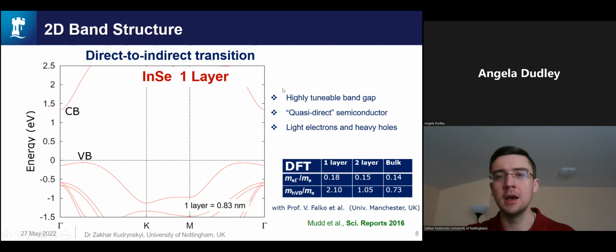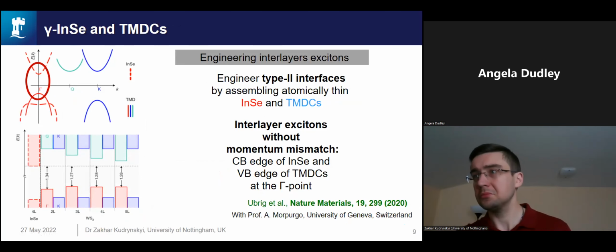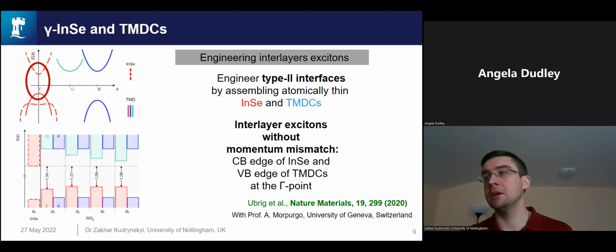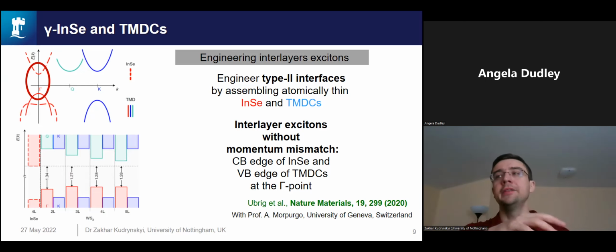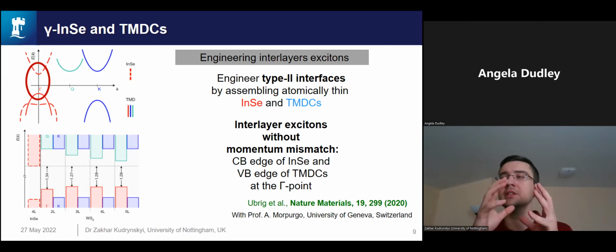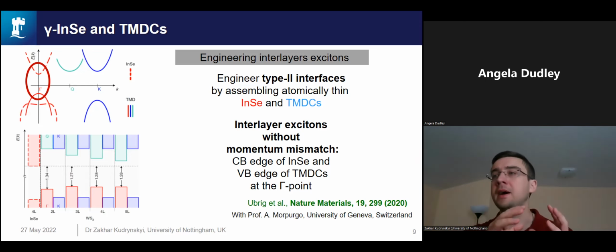Another important aspect here is that it has also been explored recently. This is a possibility of combining this 2D material, indium selenide, with transition metal dichalcogenides, as the two systems have quite different electronic band structures. And here the idea is to engineer type 2 interfaces by assembling atomically thin layers of indium selenide with transition metal dichalcogenides to create an interlayer exciton, with electrons at the conduction band edge of indium selenide and holes in the transition metal dichalcogenides that are also confined at gamma.